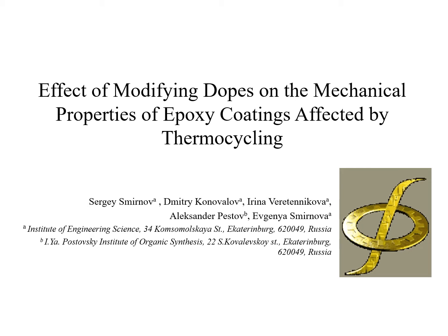Due to the differences between the linear thermal expansion coefficient of the substrate and that of the coating material, the system experiences internal stress fluctuations, and this may eventually change the mechanical properties.